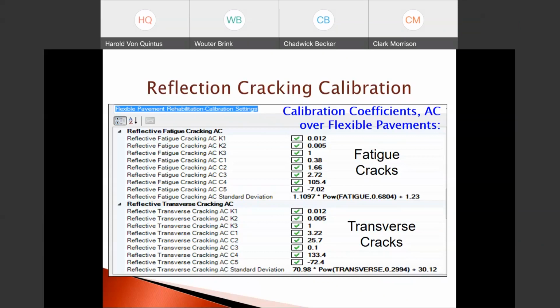K1 is the bending stress component. K2 is the shear stress component. And K3 is the thermal stress component that we showed earlier in terms of the contributions of each of these components to the prediction of reflection cracking. And as a reminder, K2, the shear component, is the most important for the majority of the rehabilitation strategies and designs that a designer is going to encounter or use.